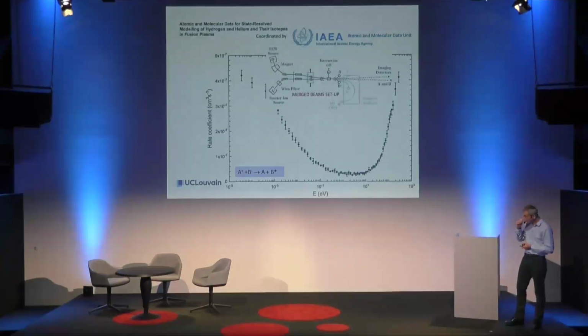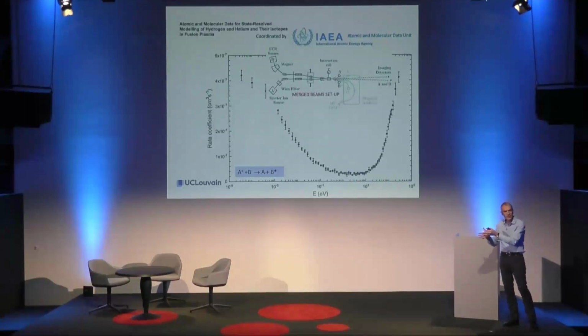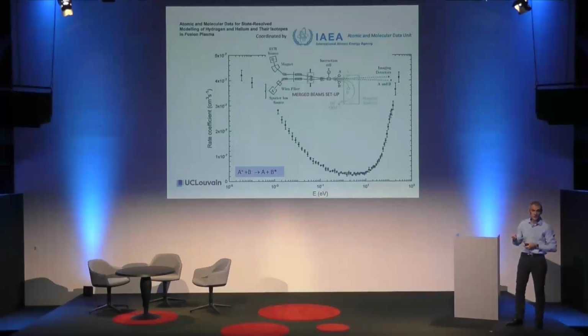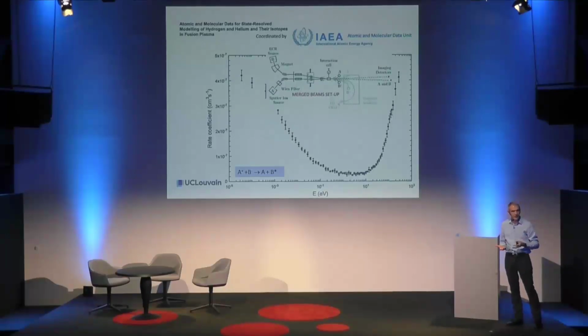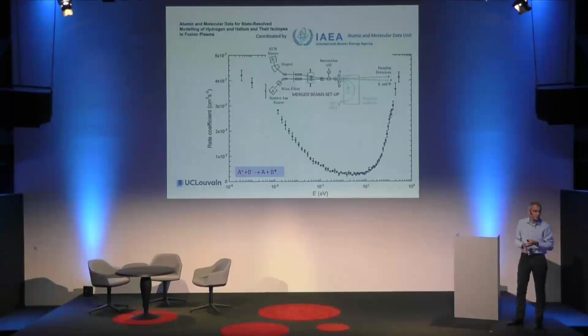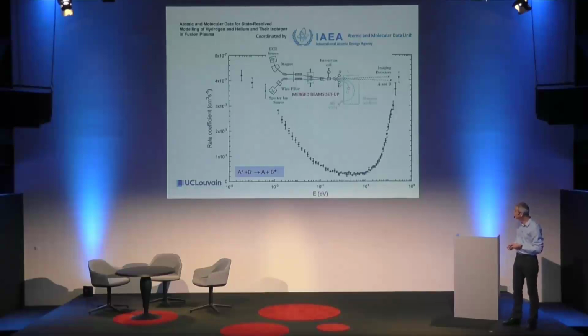And the other studies concern the heavy particles. How would an ion interact with a neutral molecule that desorbs from the walls? For that, we have developed techniques that allow us to cover a very large domain of collision energies, which is called the merged beam technique. You have beams traveling together at the same speed and then interacting at very low energy. The very low energy I'm talking about is a temperature of something like 30 Kelvin in the beam, but we can as well go to millions of degrees, provided the beam velocities are different enough. So this is the kind of measurements you can perform.